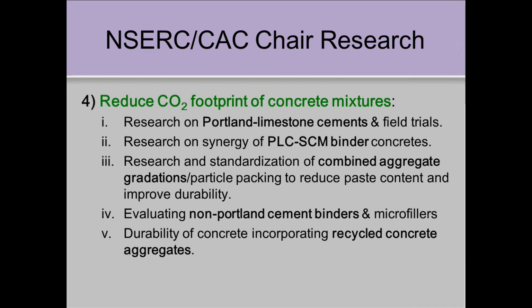And particularly on the 10%, reducing the CO2 footprint of the concrete that's used in the first place. We've got a lot of students working on Portland limestone cements, which were introduced, and I'll talk about that. Looking at the synergy of these Portland limestone cements with traditional supplementary materials like fly ash, slag, and silica fume in multiple blend binders, which are becoming more common. We're looking at combined aggregate gradations, which is not new, but it's new to the Canadian code, to try to optimize the combined aggregate gradation, because if you can do that, you can reduce the required cement content and actually improve the properties of concrete, reduce the permeability, reduce shrinkage, and other things that are good. And we're looking at non-Portland cement binders, alkali activated materials, and we're doing work with recycled concrete aggregates.